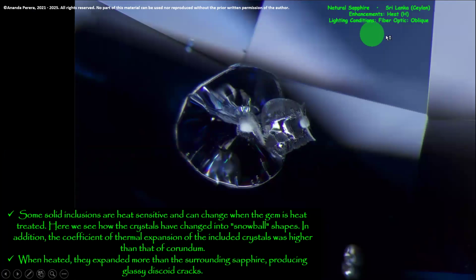The lighting condition here is oblique fiber optic. Sapphire is Sri Lanka sapphire, that is Ceylon sapphire. Heated stone. Look at the snowball here and the glassy discoid here. This is a glass-like discoid. In the center, there is a snowball-like thing. So some solid inclusions are heat sensitive and can change when the gem is heat treated. It has happened here. Here we see how the crystals have changed into snowball shapes.